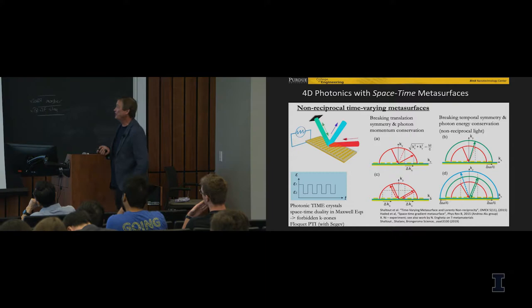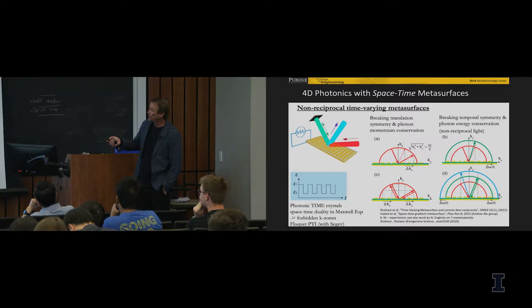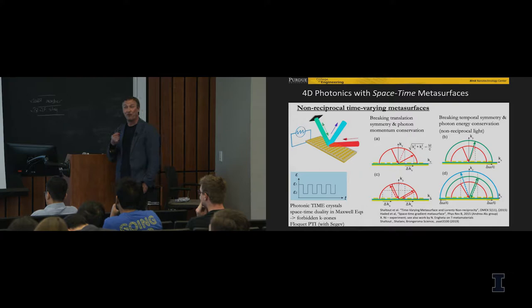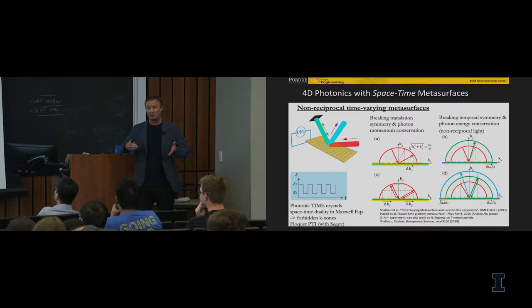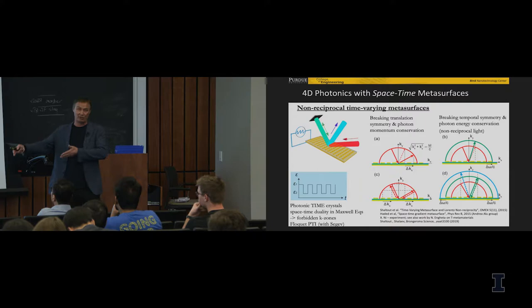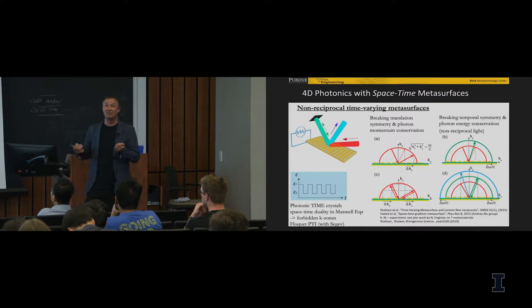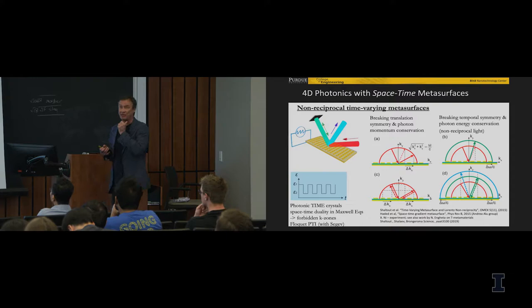Which means that in this case, light, let's say, reflected from such a metasurface, instead of going in the regular direction, would go in some other direction. You basically break photon momentum conservation, because you introduce additional momentum associated with the phase shift provided by these antennas that depends on spatial position. Therefore, you introduce delta K, and as a result, you could send light in any direction, both reflected light and refracted light. So that's the idea of metasurfaces.